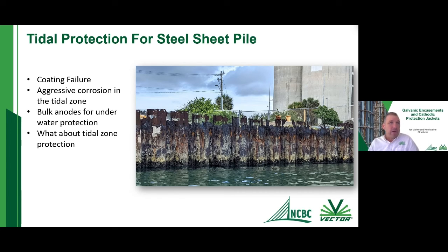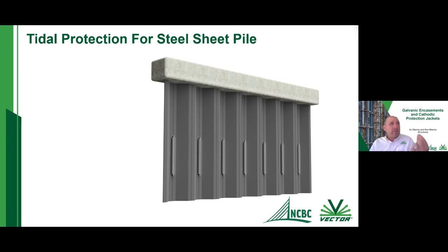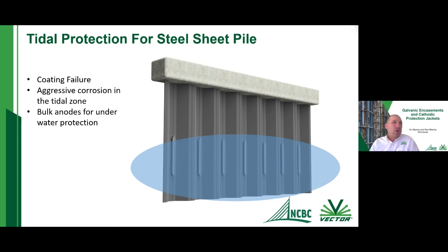So what we have here is obviously we have coating failure. Obviously the sheet pile wall has experienced a ton of corrosion here. It's probably well beyond being fixed or repairable. And so typically what is done in these circumstances is you would have some sort of a concrete cap on the top of it. And then you would also have some bulk anodes that would be attached to your sheet pile wall within your submerged zone. So this is also a very aggressive area for corrosion.